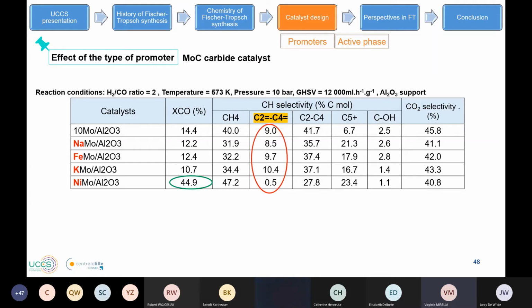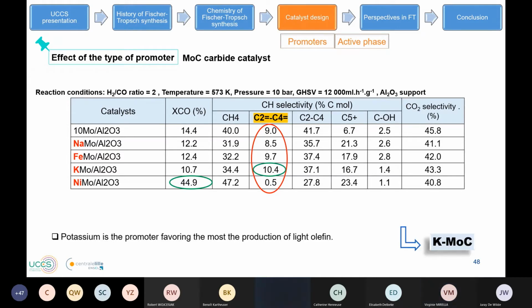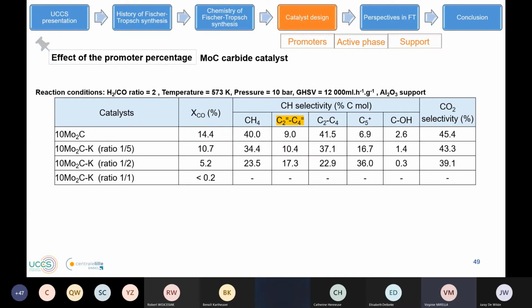But when we have a look at the selectivity of olefin, we observe that we have higher olefin selectivity when we promote our carbide catalyst with potassium. So potassium also here for molybdenum carbide catalyst is one of the most interesting promoters. Then also with potassium molybdenum carbide, we have varied the amount of potassium because before with molybdenum sulfide, we have seen we have an optimum.